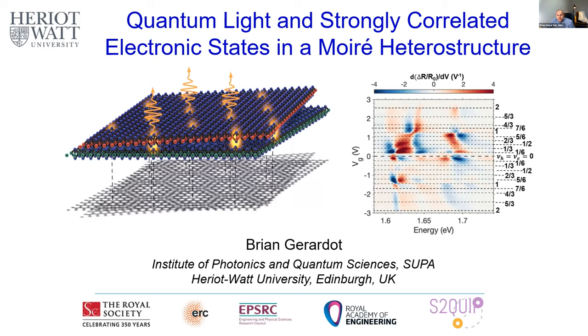I'll make a few comments about why we like the TMDs. They're compounds in which a single monolayer consists of a heavy metal in the center, with a layer of chalcogen atoms above and below. If you look at the 2D sheet from above, it has the same hexagonal structure, similar to graphene and boron nitride. In this case, we have a broken inversion symmetry in the center that opens up a gap. It turns out this gap can become direct in the limit of a monolayer, so we can treat these as direct band gap semiconductors. What's different here is that we have a heavy metal in the center with predominantly d orbitals contributing to the bands. So it leads to a large spin orbit coupling that splits the bands as well, and this leads to spin valley locking.